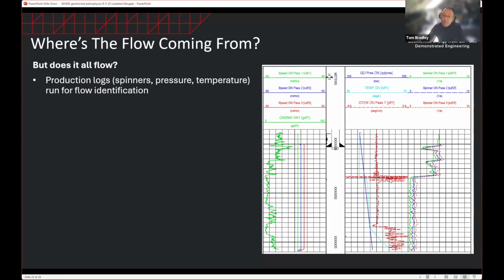For those of you familiar with production logs, I presented the temperature on this track with differential temperature here, and your spinners over here. The way to read this is if your spinners are reading the same value, this means no flow is coming into the wellbore. Where you have a sudden change in the spinners, here it's going from low to high, this means that significant flow is coming into the wellbore. You can also see this on the temperature log, which is this dashed curve here. You have a significant temperature change at the same depth.